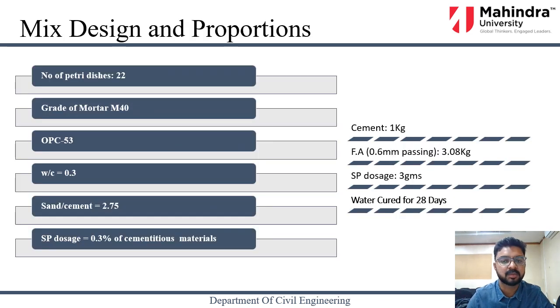This is the mix design and the proportions. As you can see, the number of petri dishes is 22. We have considered the M40 grade of concrete, OPC 53 cement, water to cement ratio of 0.3, sand to cement ratio of 2.75, and superplasticizer dosage of 0.3 percent. And here you can see the quantities that we got: cement of 1 kg, fine aggregate passing through 0.6 mm is 3 kg, SP dosage is 3 grams, and using water we have cured it for 28 days.